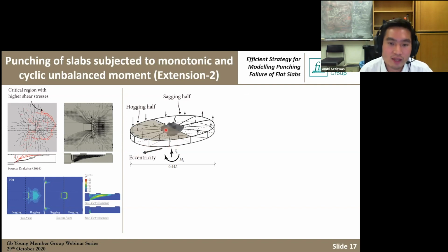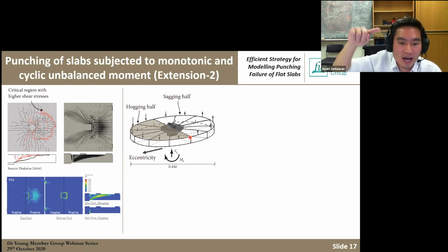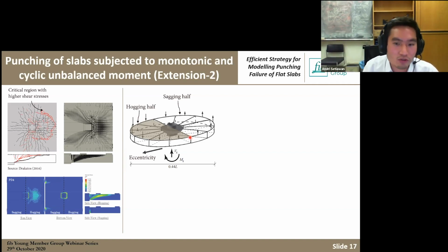So what we do is that when we have a monotonic loading, we assume that the redistribution can only happen along the half of the slab, which is only along the hogging half. So when the last joint at the slab center line fails, we assume that, okay, redistribution is done, because otherwise it will continue to redistribute to the sagging half, and in reality it won't happen because you need to have very ductile slabs in order to be able to redistribute to the sagging half, and it doesn't make sense.